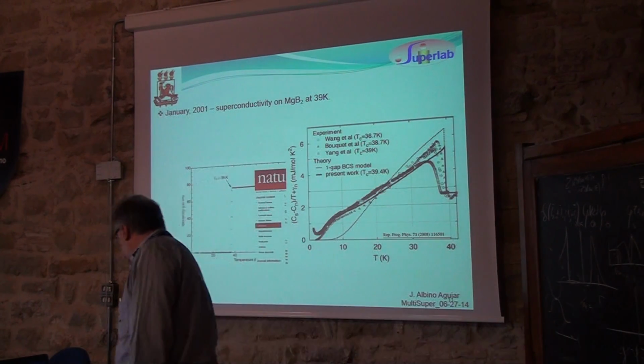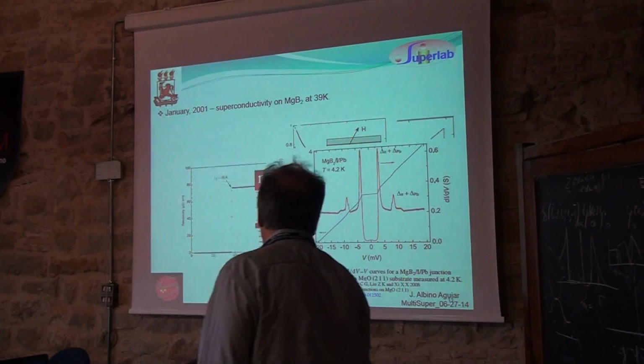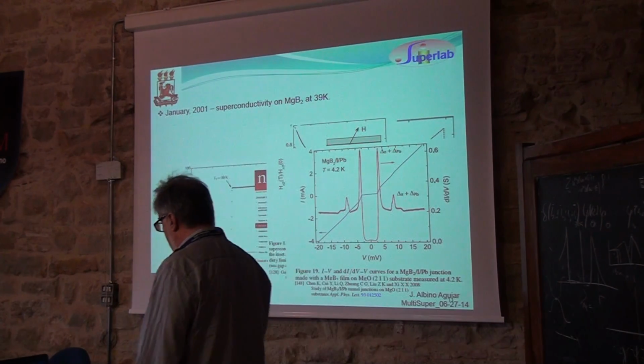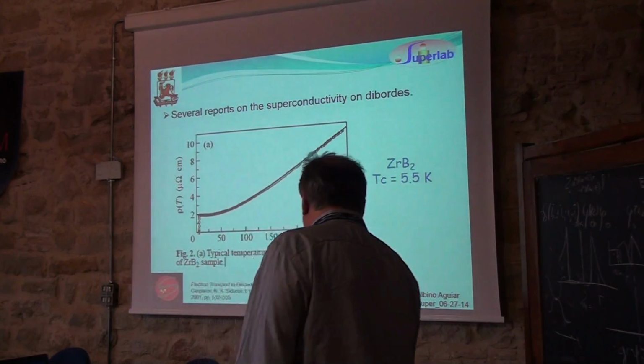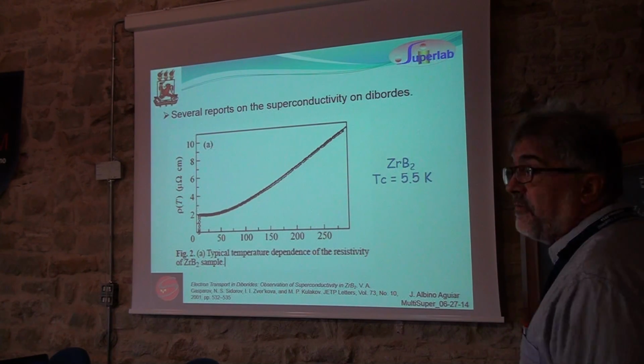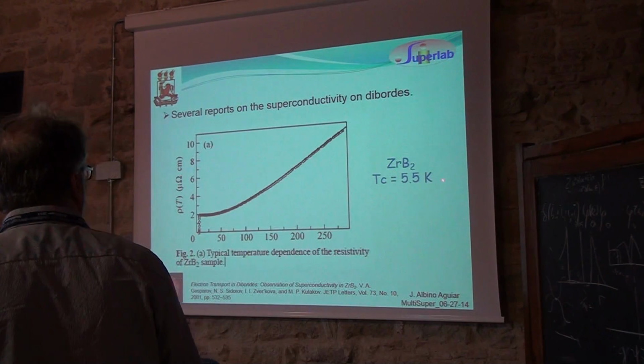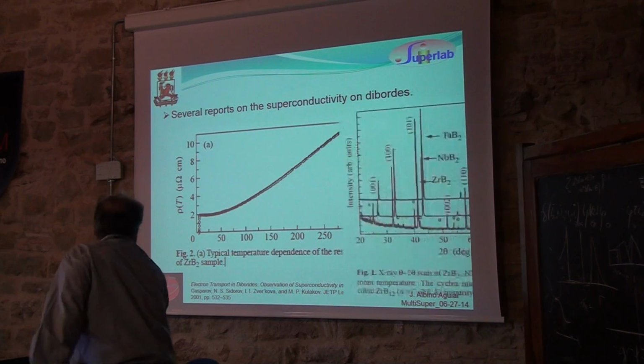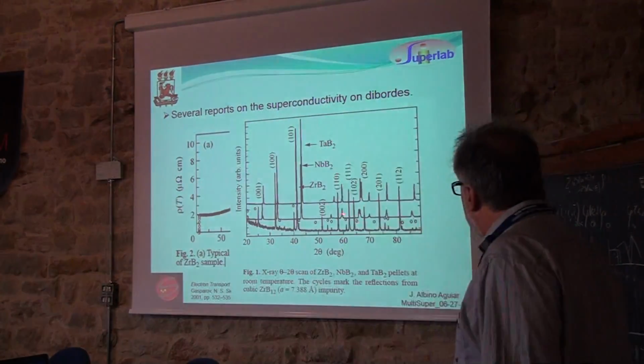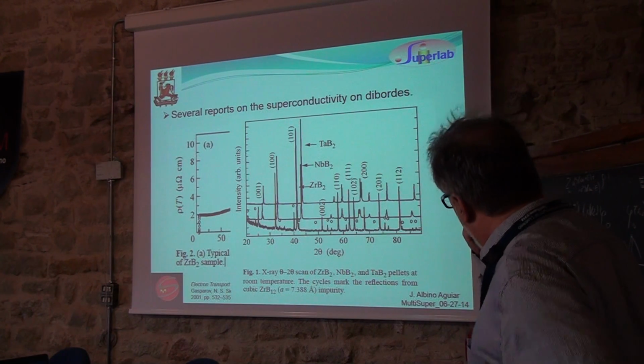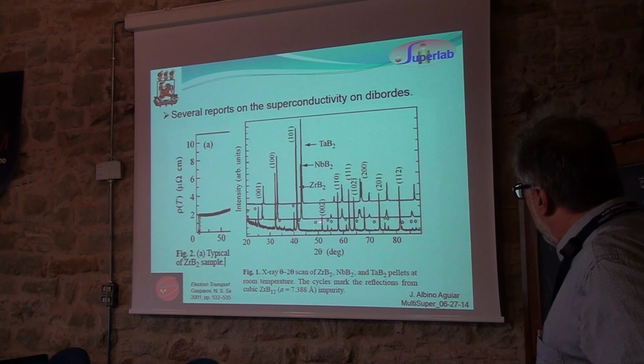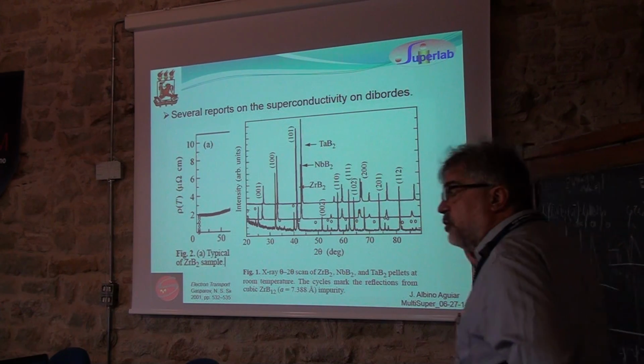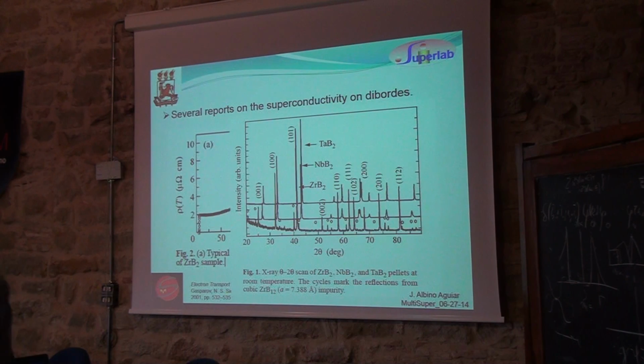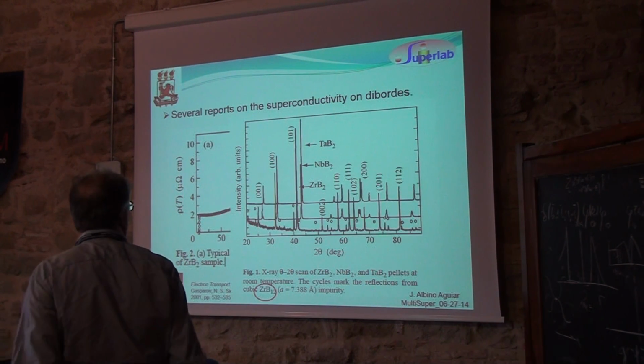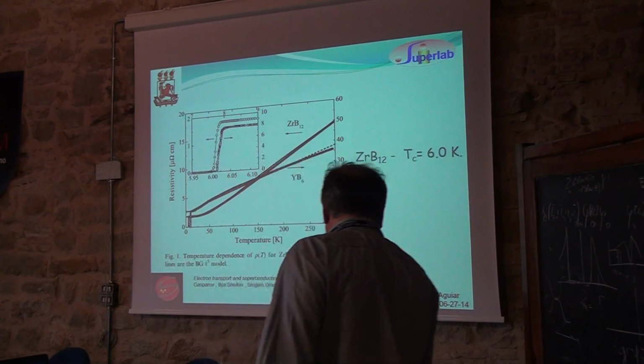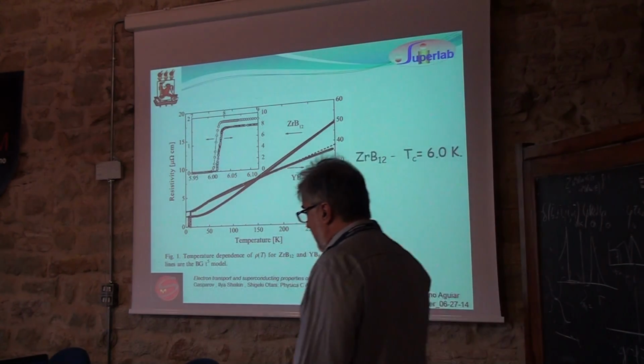And then later on, we have to get clearly detected. So we decided to look before. There is one report about superconductivity in zirconium diboride, with a transition temperature of 5.5, and also with niobium. But you see here, this is the X-ray diffractogram for this material. You see the impurity phase, and this impurity phase is due to zirconium dodecaboride, that is superconducting at about 6K. So we have a look.